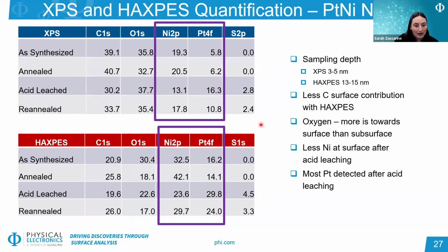Looking at the nickel and platinum data, we see generally that there is a change with the annealing process. We see slightly more nickel in both the XPS and HAXPES data, and then slightly less nickel once we acid leach and reanneal. And we see kind of the opposite trend, where we see more platinum at these later steps in both samples, but we also see slight differences in the relative amounts of these metals, where we're detecting a lot more nickel deeper into the sample with the HAXPES source.